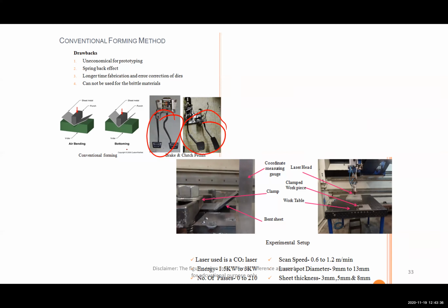We went for very different materials with different thicknesses. The thickness ranged from 3 mm, 5 mm, 8 mm, and even 10 mm. We used a carbon dioxide laser with a power of 1.5 kilowatt to 3 kilowatt. We varied our passes from 0 to 210, with a scan speed of around 0.6 to 1.2 meter per minute, and a laser spot diameter of around 9 mm to 13 mm.